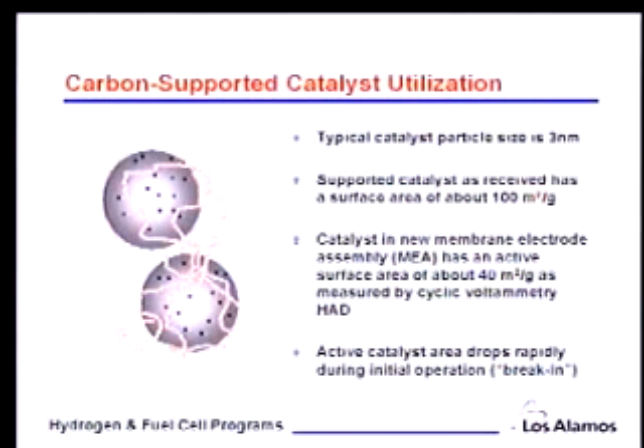The catalysts we're using today have a particle size of about 3 nanometers when we get them from the manufacturer. As received, they have an area then of about 100 square meters per gram. By the time we make this composite structure, and what we do is we solubilize the ionomer, and we put it in solvents that evaporate, and we make an ink, and we put it on a decal, then we hot press that onto the membrane. By the time you do all that, you're down to about 40 square meters per gram.